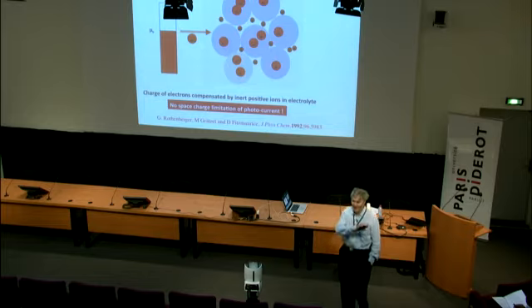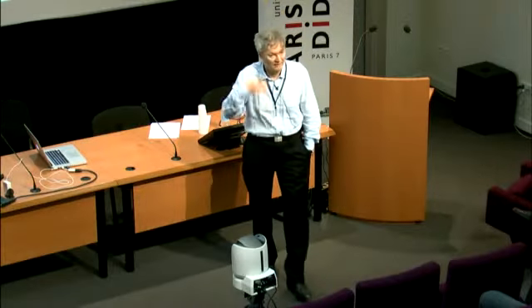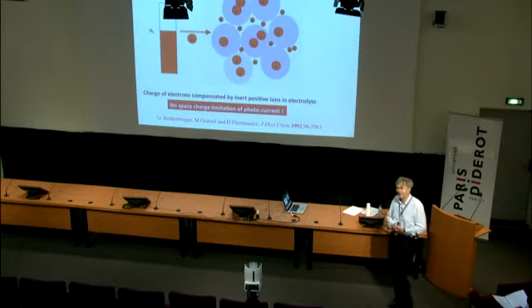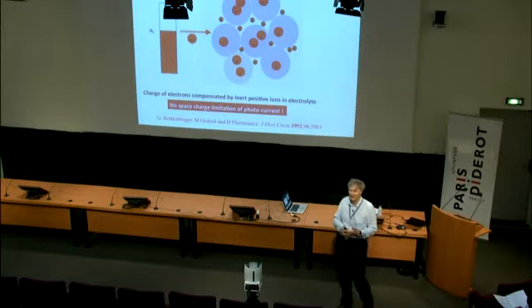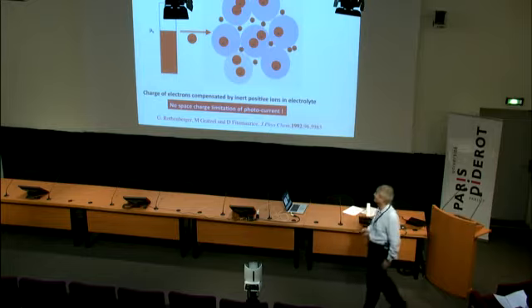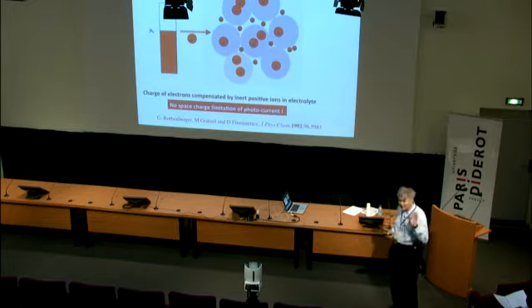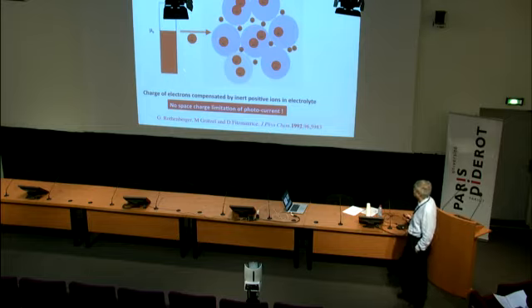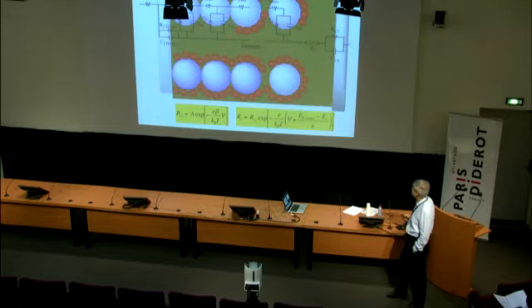If you had a bulk film that's flat, you would have to dope it, and in the sensitization there would be issues of quenching of the excited state by the electrons that are used to dope. So all sorts of optoelectronic interferences, if you have to dope the film, but we don't. We don't dope it. We just use insulating particles. They get doped by the electron injection from the dye, and we can screen those charges by the electrolyte.